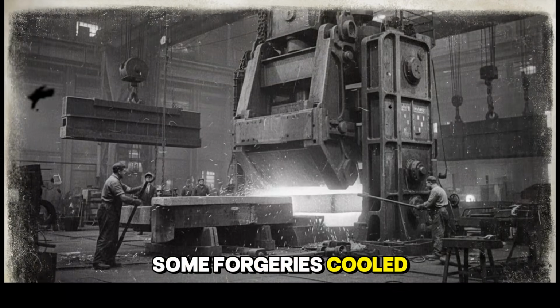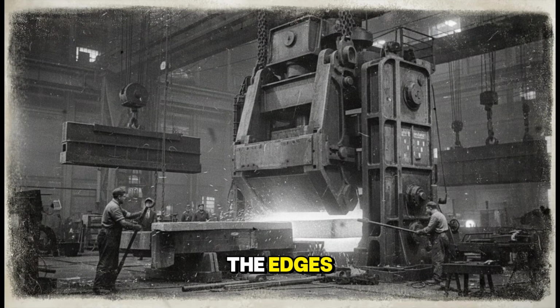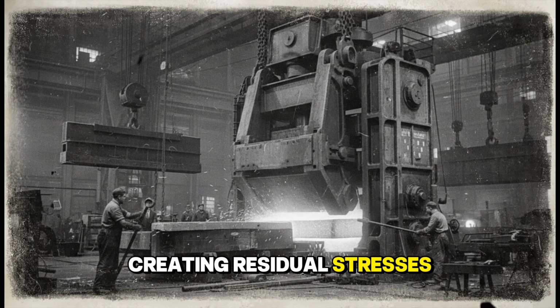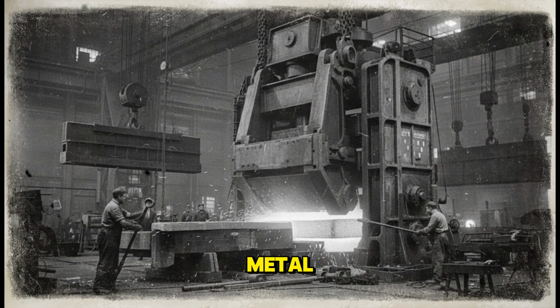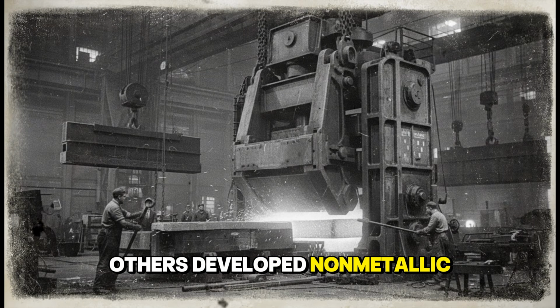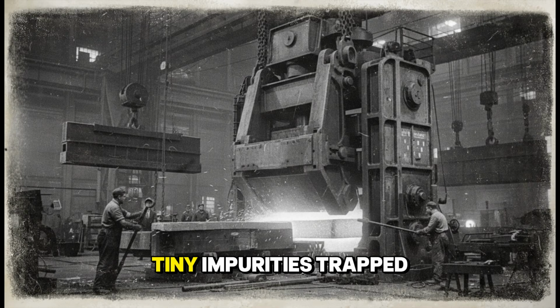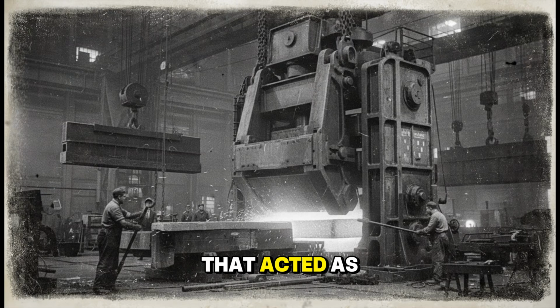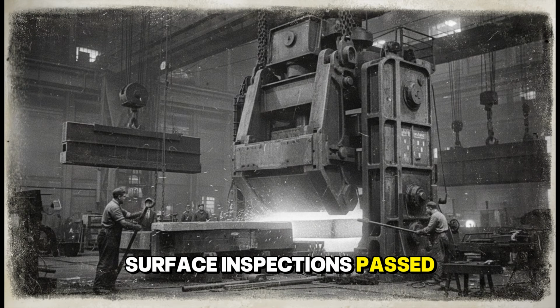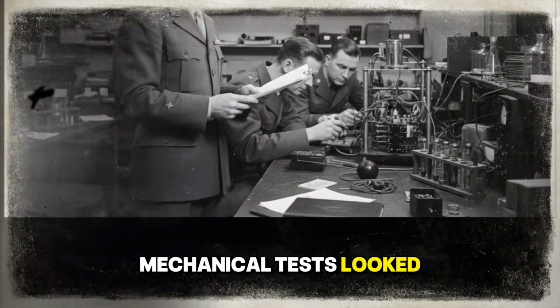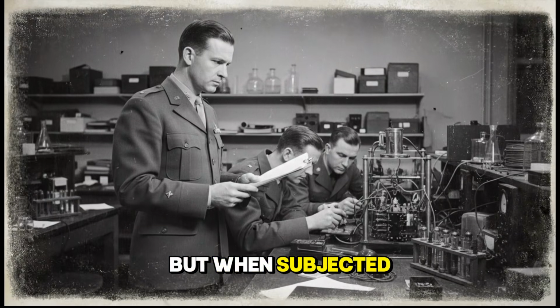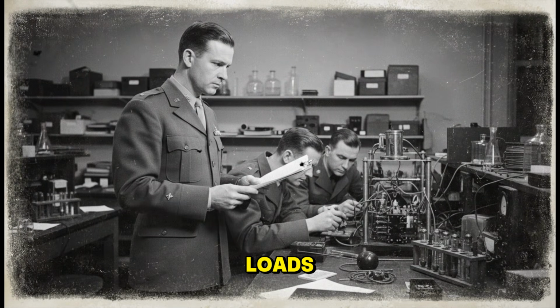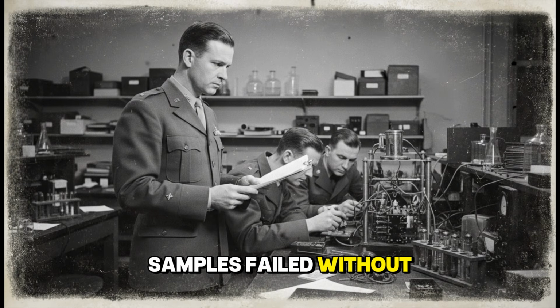Some forgings cooled too quickly at the edges and too slowly at the core, creating residual stresses locked inside the metal. Others developed non-metallic inclusions, tiny impurities trapped during pouring or forging that acted as crack initiators under pressure. Surface inspections passed. Mechanical tests looked promising, but when subjected to simulated depth loads, samples failed without warning.